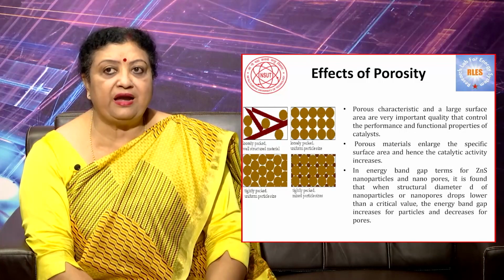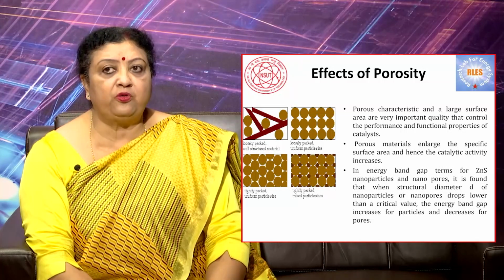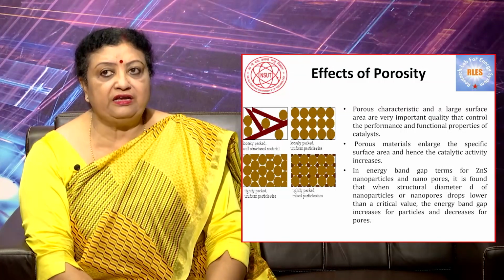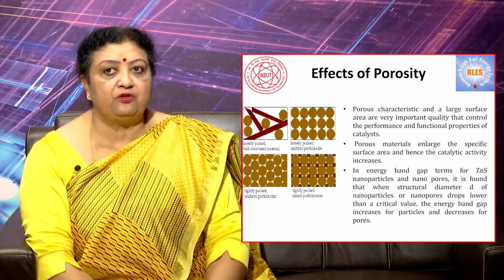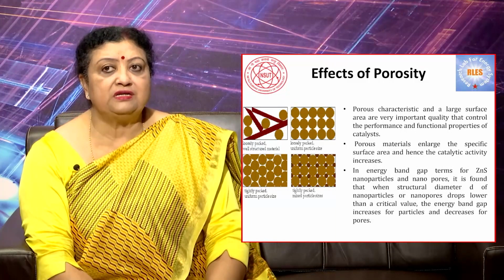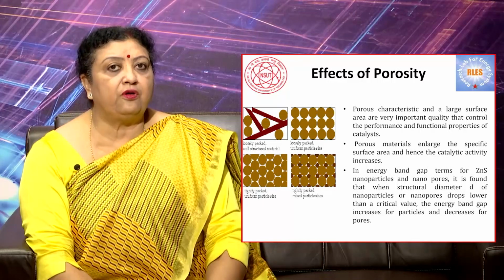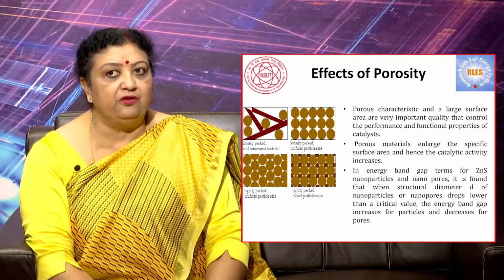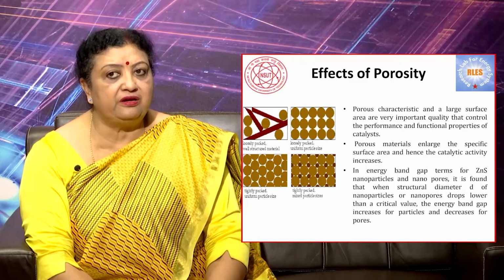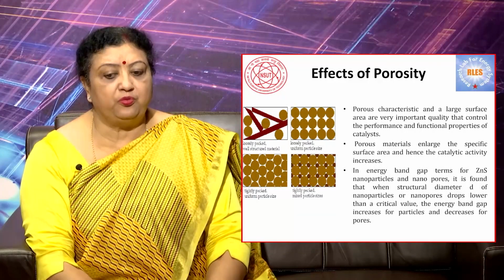In terms of energy band gap for ZnS nanoparticles and nanopores, it is found that when the structural diameter d of nanoparticles or nanopores drops lower than a critical value, the energy band gap increases for the particles and decreases for the pores.